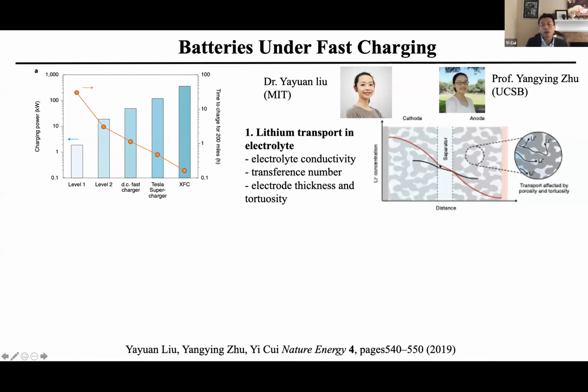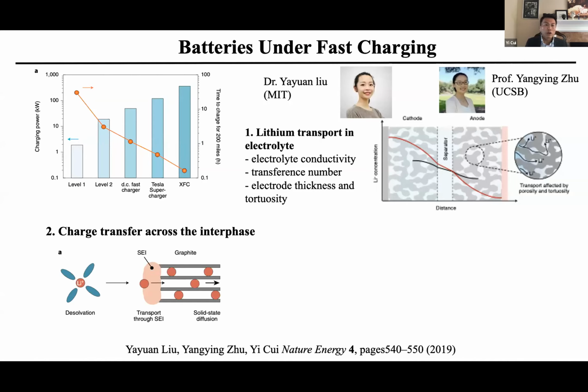Then the thickness of the electrode will affect this gradient a lot. You usually want to go to thinner electrodes to avoid these large gradient profiles. So electrolyte conductivity, transference number, electrode thickness, and tortuosity will affect lithium transport. Certainly temperature will also affect that. Higher temperature will help reduce this gradient. And then the charge transfer across the interface is very important as well. Lithium in the electrolyte is solvated by solvent molecules, and it needs to get desolvated. Desolvation will take place across the SEI interface, and then the lithium is transported into the graphite. All these processes can be affected by temperature as well.